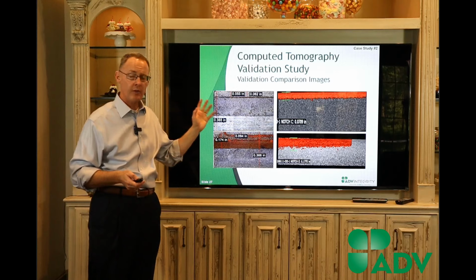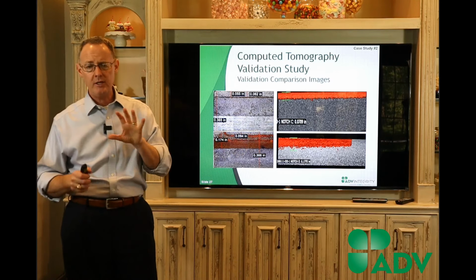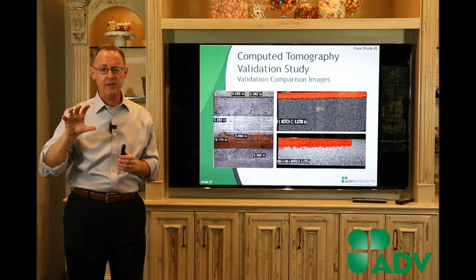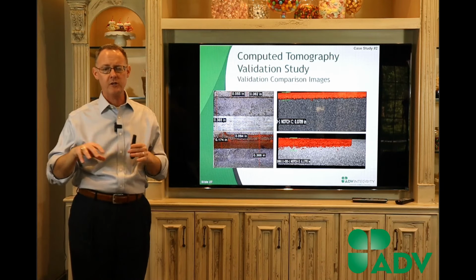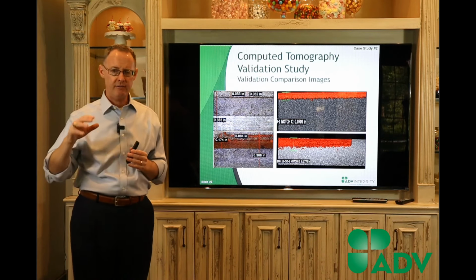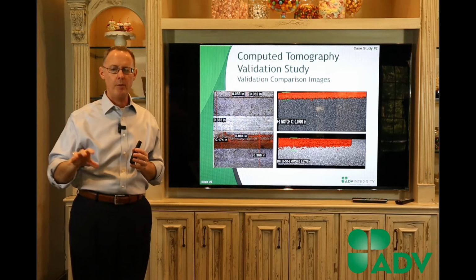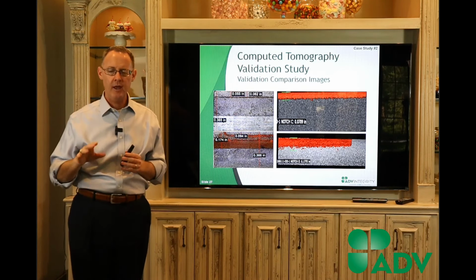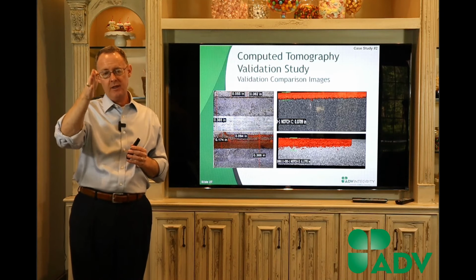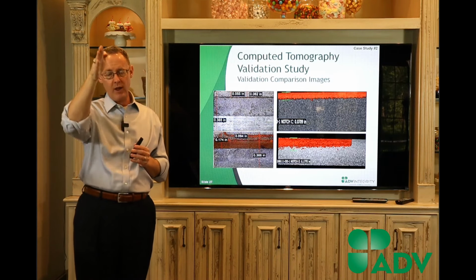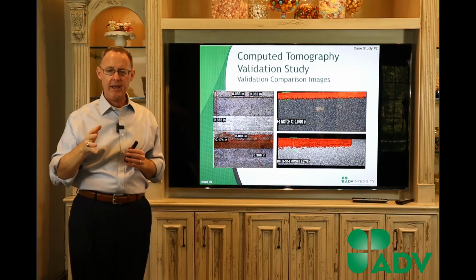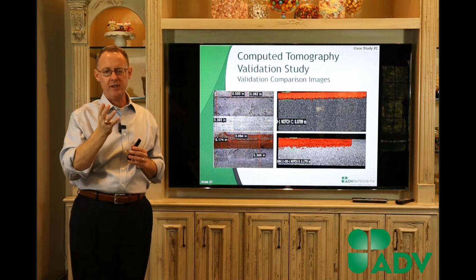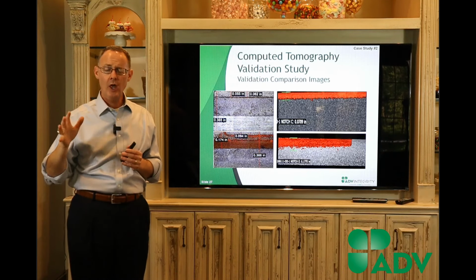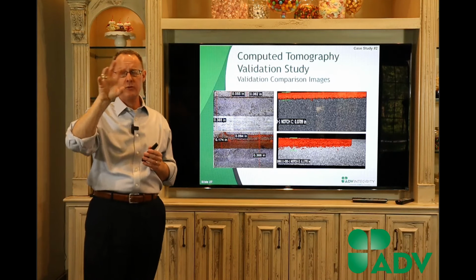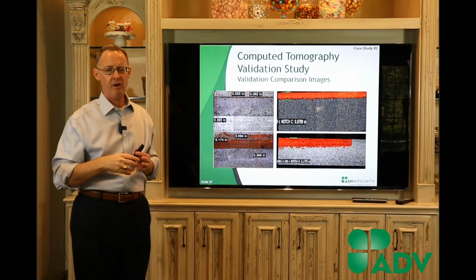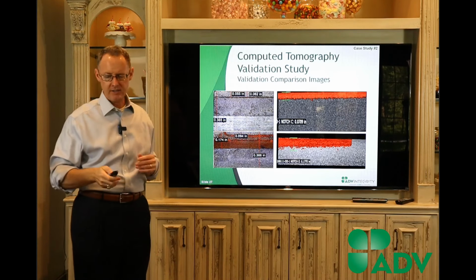So these are the images on the right that we get from James. And so he's running his inspection technology that is called computed tomography, and you can Google it. It's used in other industries, but I think for the pipeline industry, it's got a lot of promise because of the accuracy that you're able to get. What we haven't looked at is hook cracks, that they don't just run radially, they actually curve away from a radial plane, and it's practically impossible to get that with conventional NDE technologies. Well, with the computed tomography, because you get a three-dimensional image, you can see that kind of morphology of the crack.